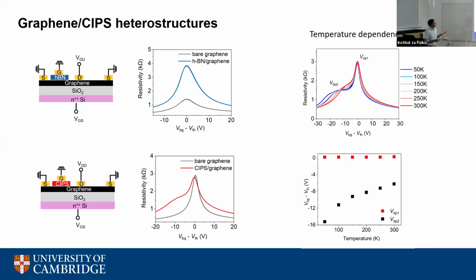And you can see that the second peak is strongly dependent on temperature. So at 50 Kelvin, the peak is quite far away from the main Dirac peak, which shows that this doping effect is quite pronounced and localized at low temperatures. But as we increase the temperature, the doping becomes more delocalized, and you can measure it in the main graphene channel and we move closer to the main Dirac peak. And this is just extracted from this graph. This is the threshold voltage minus the backgate. You can see that the second peak is coming closer to the main Dirac peak as you increase the temperature.